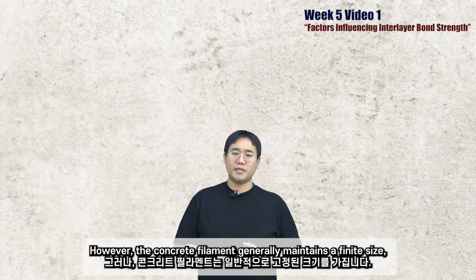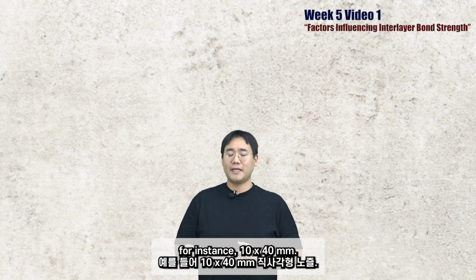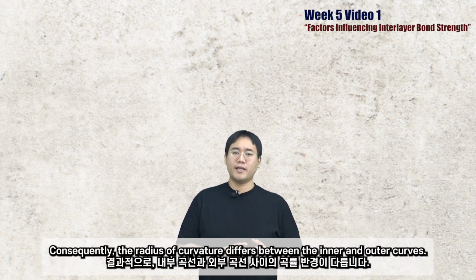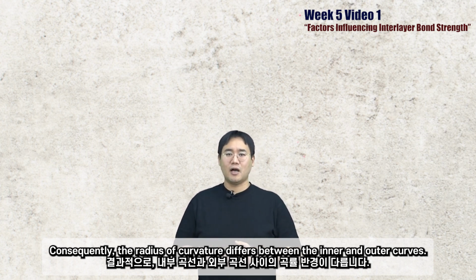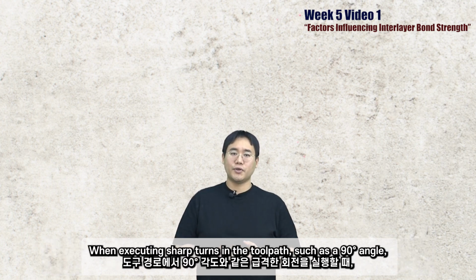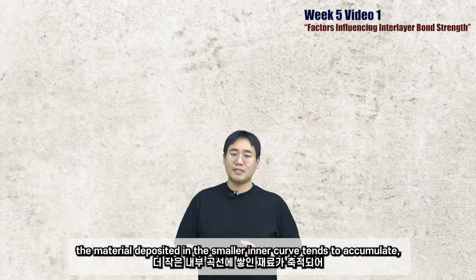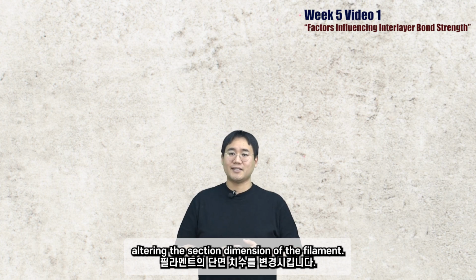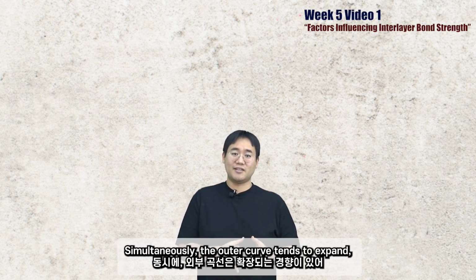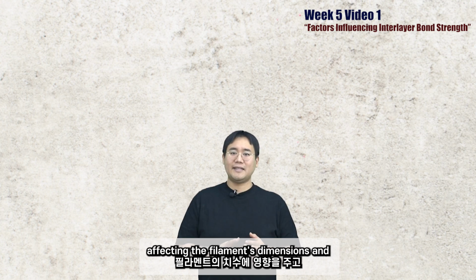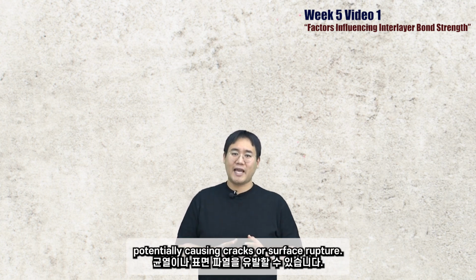However, the concrete filament generally maintains a finite size, for instance, 10 by 40 millimeters in rectangular shaped nozzles. Consequently, the radius of curvature differs between the inner and the outer curves. When executing sharp turns in the tool path, such as a 90-degree angle, the material deposited in the small inner curve tends to accumulate, altering the section dimensions of the filament. Simultaneously, the outer curve tends to expand, affecting the filament dimensions, potentially causing cracks or surface ruptures.